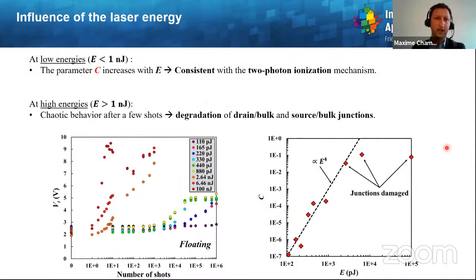In order to do so, we have evaluated the influence of the laser energy, as you can see here. Same kind of graph: the threshold voltage as a function of the number of shots. And one can see that for low energies, the parameter C increases with the input pulse energy, which is consistent with the two-photon ionization mechanism, because the more the energy, the more the ionization, of course. One can also note that at high energies, there are some chaotic behaviors after a few shots, which are related to the degradation of the drain-bulk and source-bulk junctions.